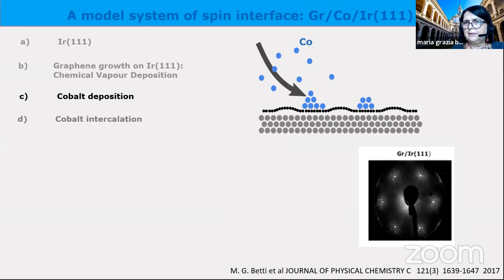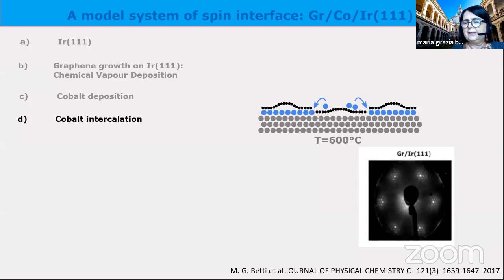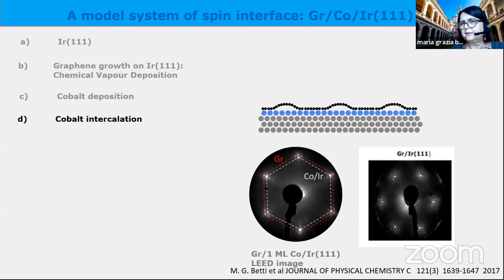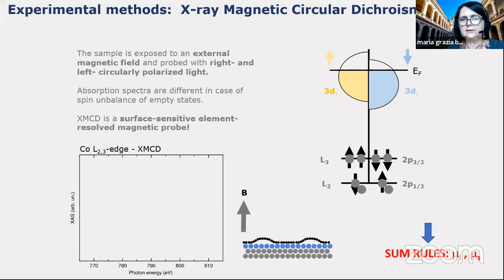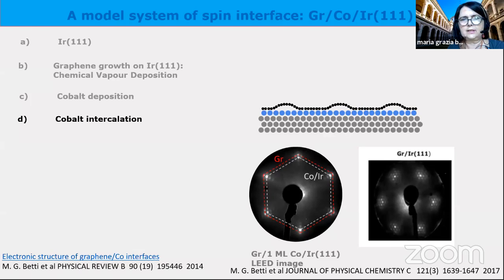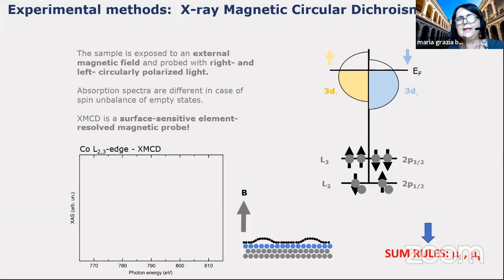Then we put cobalt on, and with annealing at 600 degrees, we will intercalate cobalt underneath. So the temperature is important because if the temperature is lower, you will have clusters of cobalt on graphene. If you have a higher temperature, you will have an intermixing of cobalt with iridium. So if you succeed to build up this architecture, then we checked the configuration of this system.